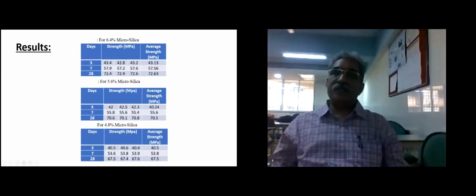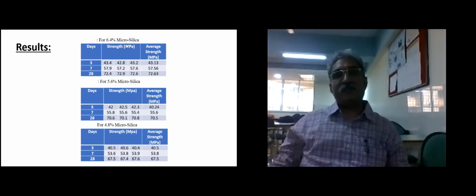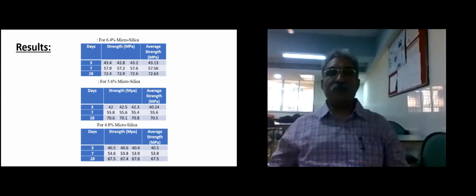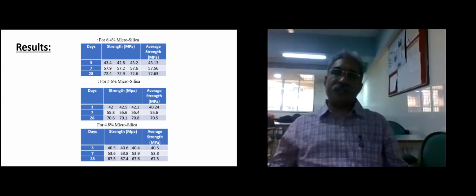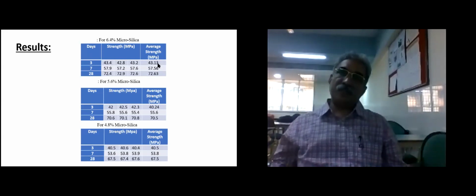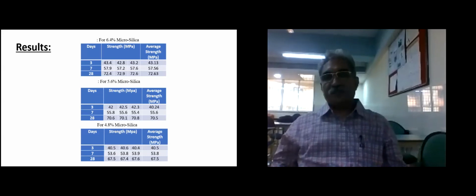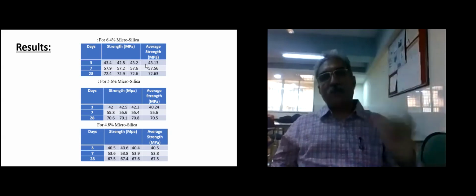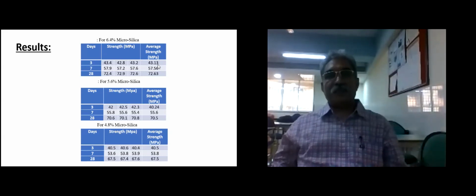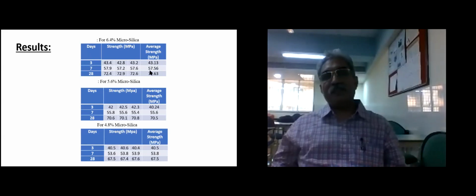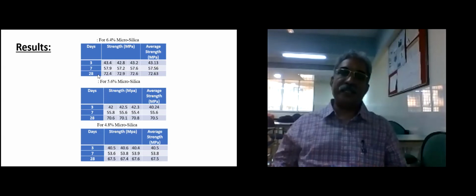Now results. What we have done here, we mix this microsilica at 6.4% by weight, not by volume, in concrete, and we checked the strength of concrete. We have taken M40 concrete. For M40 concrete mix, we have created this concrete including microsilica, and to our surprise, on the third day we got average strength as 43.13. On the 7th day it was 57.56, and on the 28th day it was